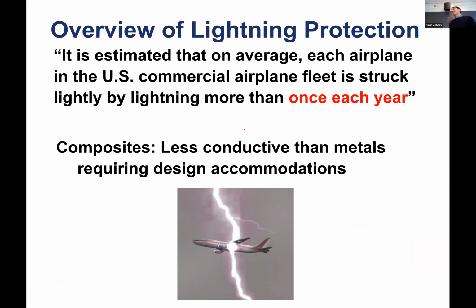Okay, so lightning strike. Every year, every aircraft would experience one lightning strike on average. That's the statistical measurement. If you have a metallic structure, the energy comes in. Metals are quite good conductors. They disperse the energy, so nothing happens to the structure. But composites, on the other hand, carbon fiber, is a good electrical conductor compared to resin, but aluminum is 1,000 times better than carbon fiber. So the energy of the lightning strike comes in, it doesn't have enough time or enough pathway to get dissipated. It gets absorbed in that location.